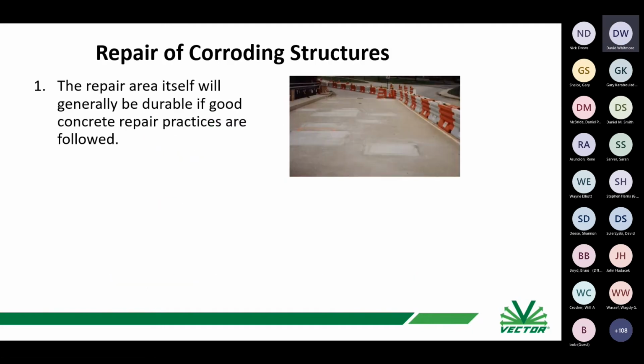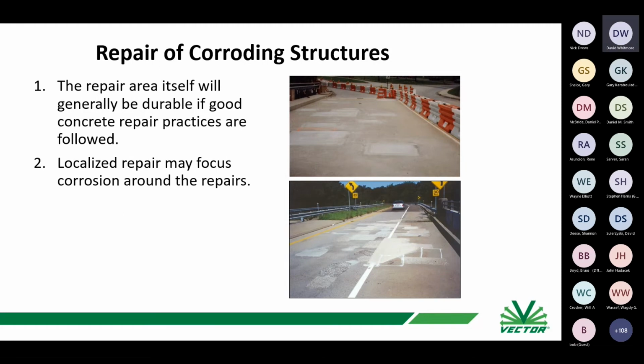And so if you go and do repairs on a structure, this is a picture from a VDOT project from a number of years ago. They've identified the repairs, they've done good quality repairs. The repairs themselves will be durable. There's no chlorides in the repairs. You're not going to have to worry about that. But the localized repairs by themselves, if you're leaving chloride contaminated concrete all around, is going to lead to secondary corrosion. People say patch accelerated corrosion, whatever, but in the areas adjacent to those repairs, there's going to be sharp voltage differences, and you'll tend to see corrosion occurring at the areas adjacent to where you've done first round repairs.